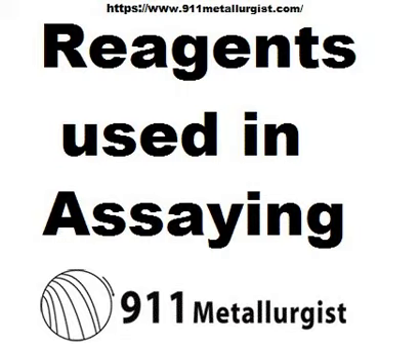Dilute hydrochloric acid is made by diluting the strong acid with an equal volume of water. This is used for dissolving precipitates obtained in the general course of analysis and the more easily soluble metals. Hydrofluoric acid — a solution in water may be purchased in gutta-percha or lead bottles. It is of variable strength and doubtful purity, and must always be examined quantitatively for the residue left on evaporation. It is used occasionally for the examination of silicates; it attacks silica, forming fluoride of silicon, which is a gas. The fumes and acid are dangerous, and glass or porcelain vessels cannot be used with it.